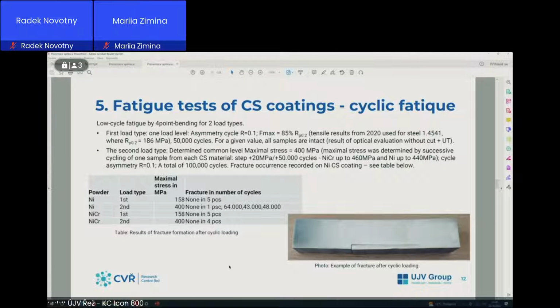For, let's say, Fmax 158 megapascal, none of 5 pieces had a fracture for both powders, nickel and nickel chrome. The second load type, in this case, on one piece of sample, we optimized maximum stress for both powders. The optimized value was 400 megapascals, and you can see nickel chrome was good, no fractures after 100,000 cycles.